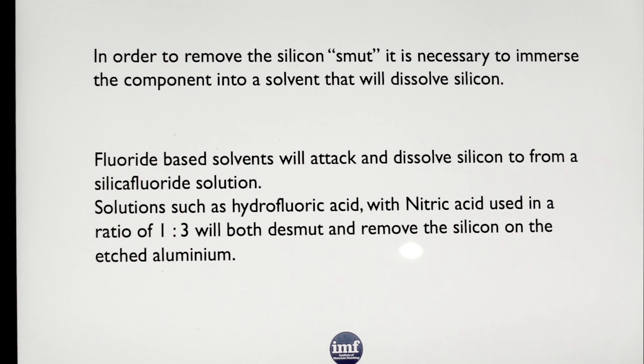and that product is a fluoride-based solvent, such as fluoboric acid, ammonium bifluoride itself, what's called a dry acid salt. Anything that will produce a fluoride will dissolve the silicon and then produce a byproduct called a silica fluoride. So you can use HF, not the nicest of things to use, or you can use dry acid salts. So you can use it as a mixture. After you're etching, you go in a mixture of nitric acid, a ratio of 1:3, and that will then remove the silica off the surface and leave you with a clean etched aluminium surface, which, bear in mind, as Jan said, immediately you rinse it, will form an oxide layer again.